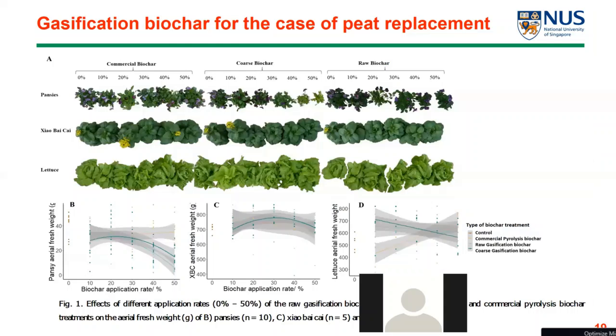Lettuce and chai grown in our study in raw and coarse biochar percentages of 10 to 30% outperformed the pure peat by as much as 130%. However, pansies, which require a low soil pH, responded poorly to the liming effect of biochar, and they were never able to achieve a stable aerial mass or produce flowers properly, equivalent to the pure peat mixture.